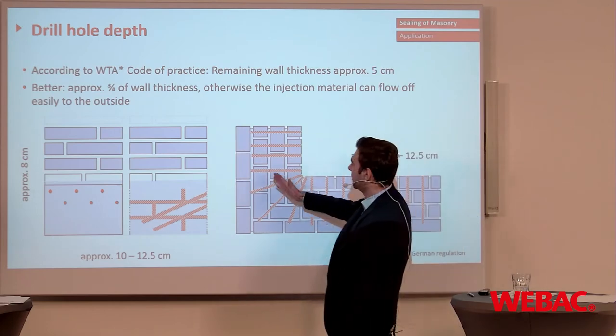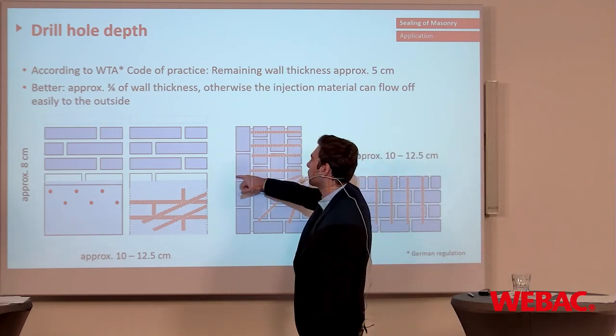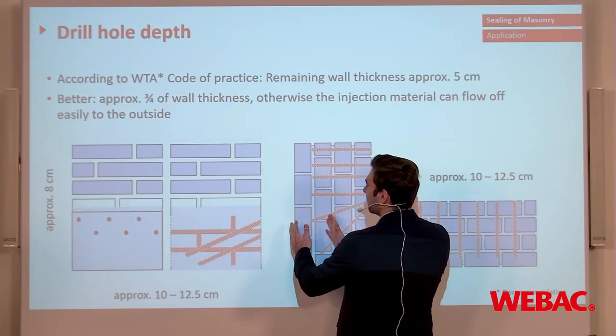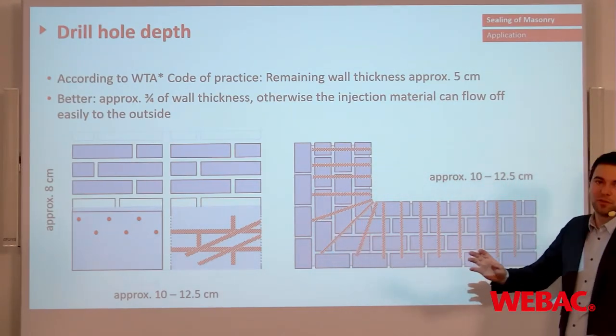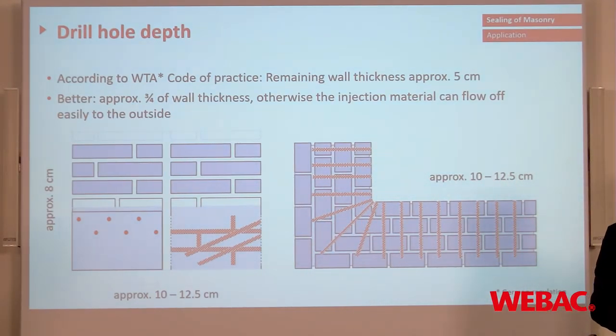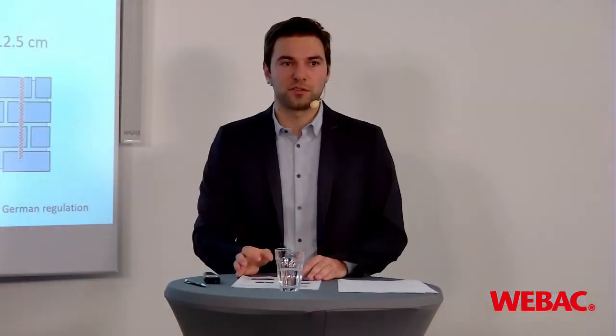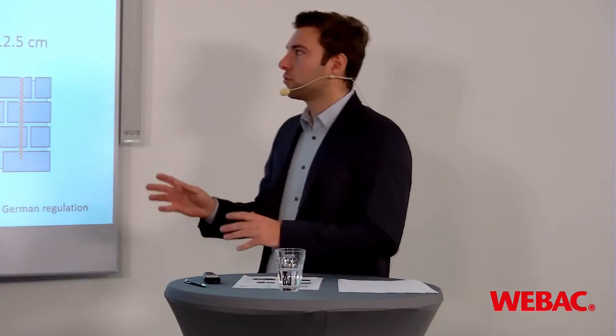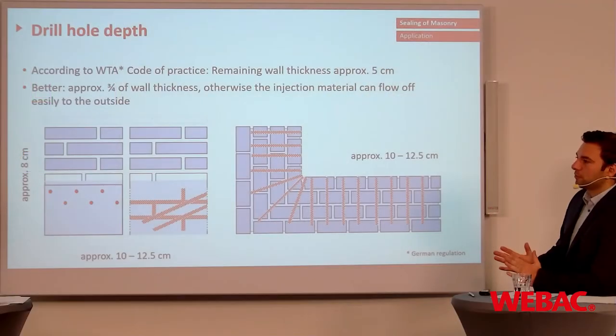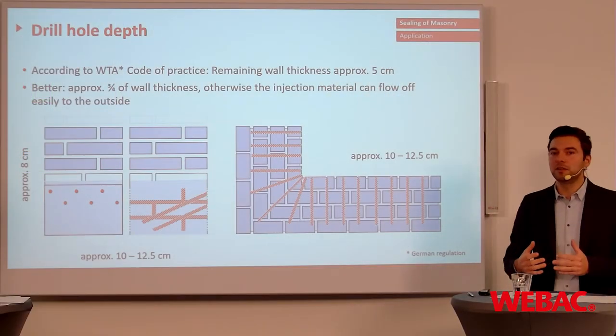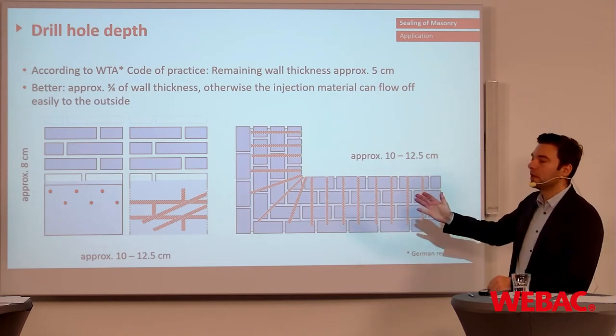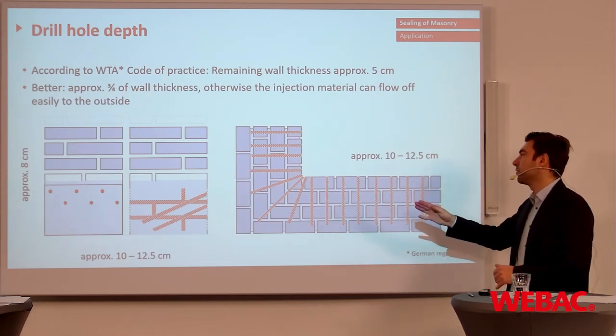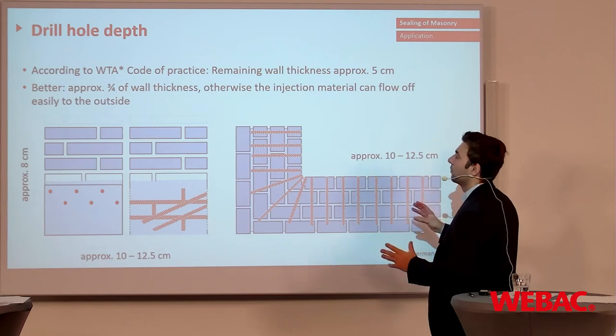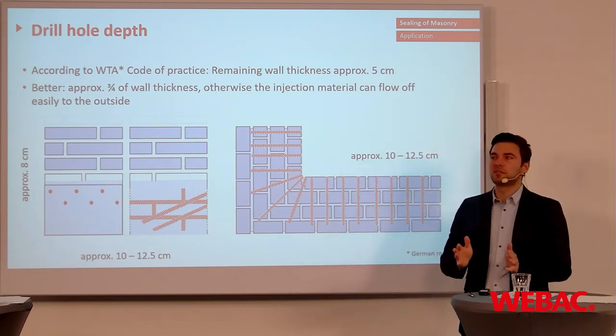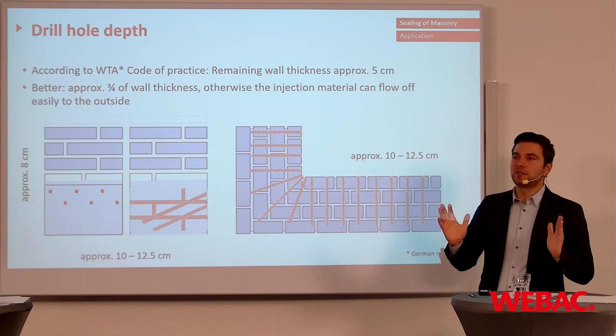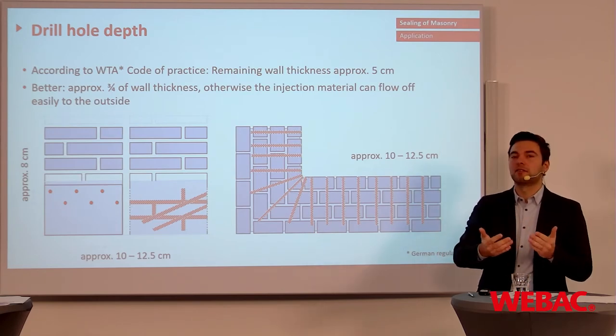So you can see it here. The drilling is not going through the structure. There has to be some space inside the structure. And the reason for that is simply that the material is looking for the easiest way to get out of the structure. If you would drill too close to the end of your structure, the material would easily penetrate through your structure, and you do not have the distribution inside your masonry. So therefore, you need to have a certain distance where the material has a back pressure, some blocking, and is able to penetrate